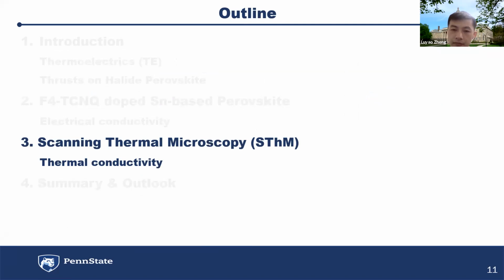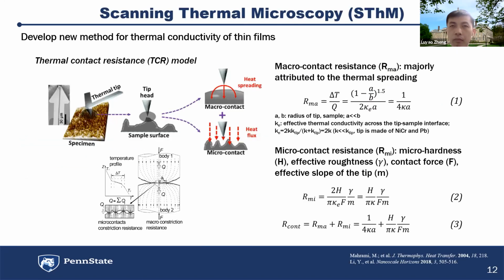So basically, it's an AFM setup coupled with some designed circuit with some thermal parts, as shown here. This model is based on the thermal contact resistance. When the tip is attached to the sample, there are two ways to transfer the heat between the tip and the sample, because the radius of the tip is very small. So the micro contact cannot be ignored in this case.